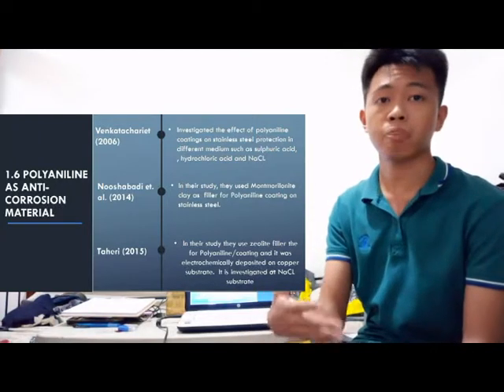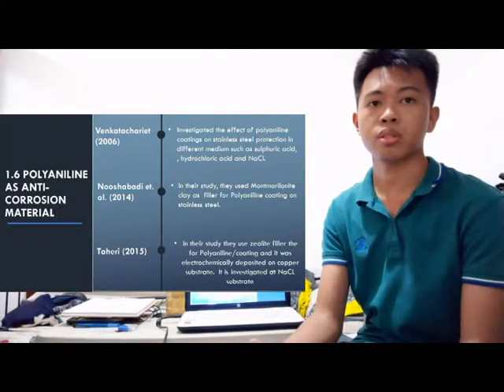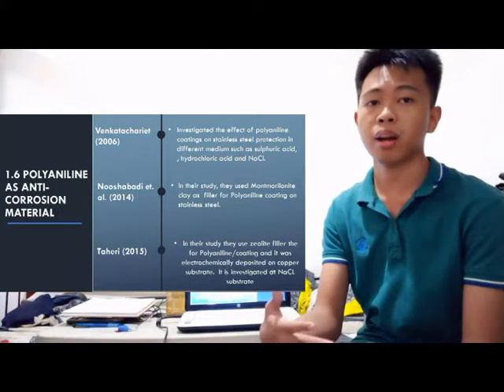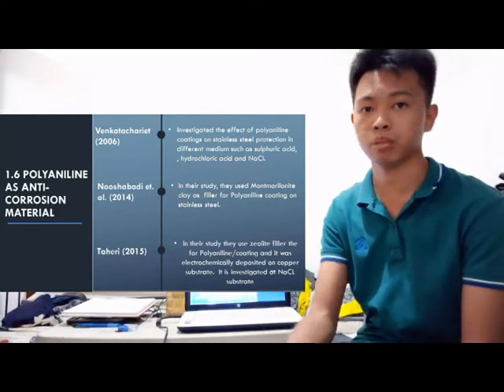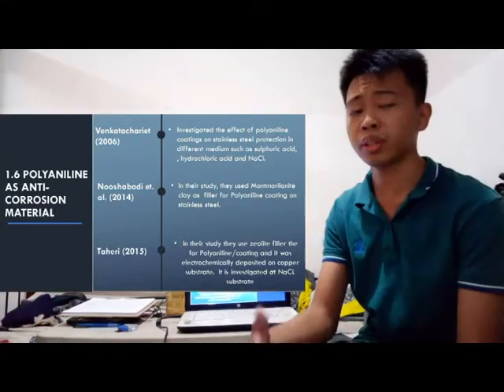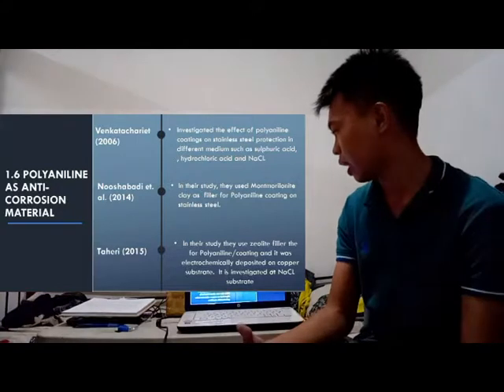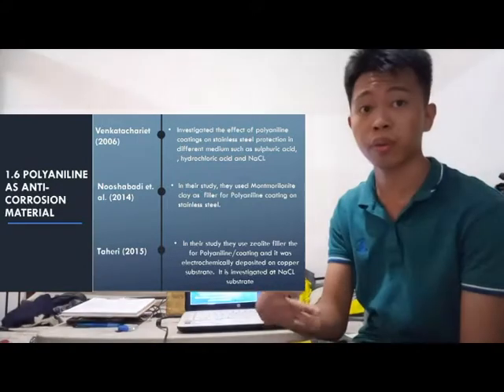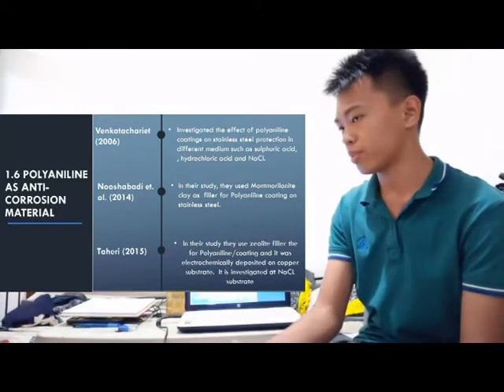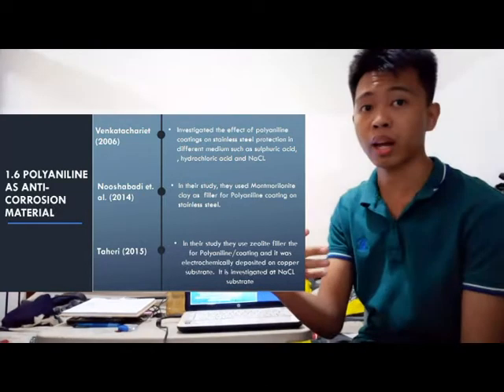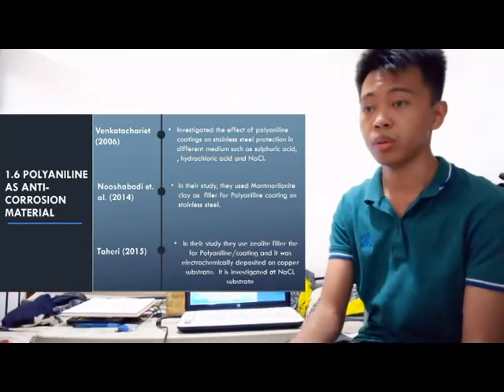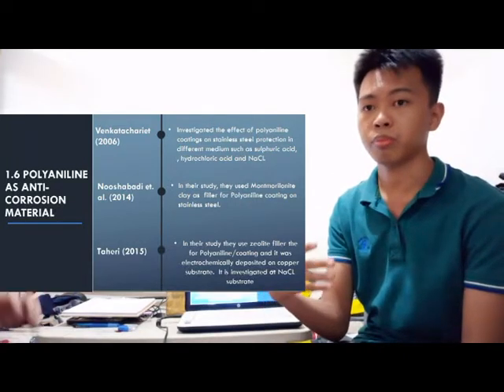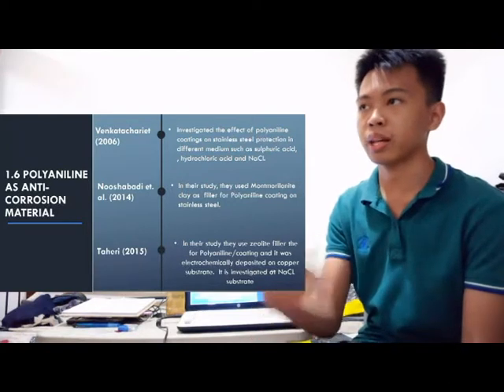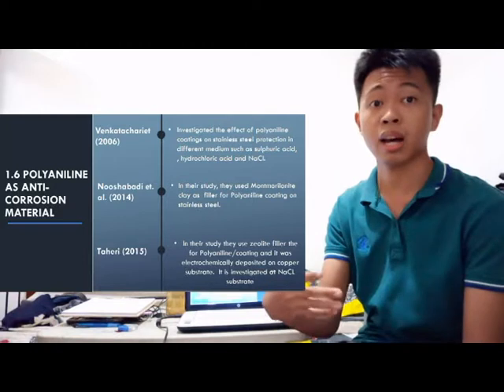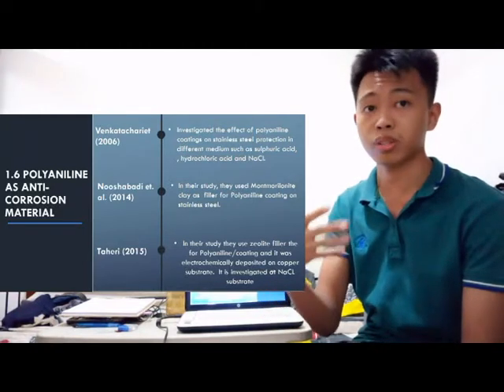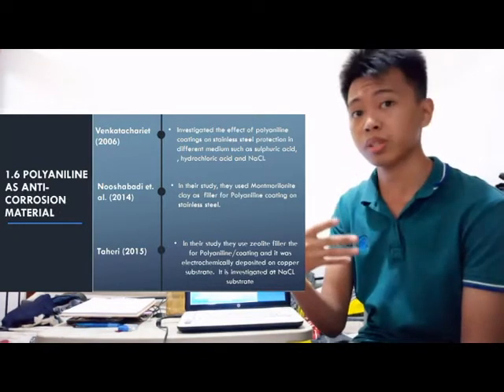So to further improve the polyaniline matrix, additives are used, and these additives can enhance the barrier ability and mechanical stability of our polyaniline matrix. In the year 2014, an author named Nooshabadi and his colleagues used Montmorillonite clay as a filler for the polyaniline matrix on stainless steel substrate. They subjected it to hydrochloric acid and investigated the anti-corrosion test. Based on the results, these Montmorillonite nanoparticles act as a barrier and can increase the diffusion pathways through which the corrosive medium passes, which can cause delay to the transport